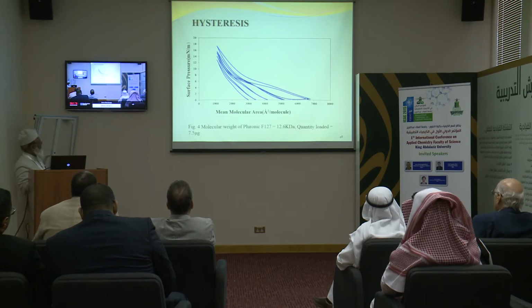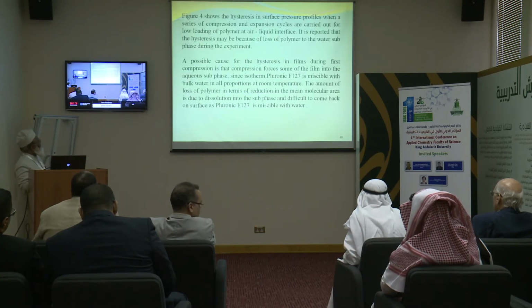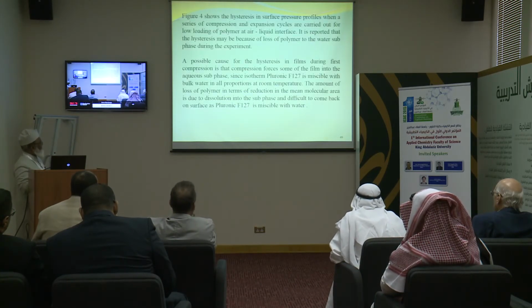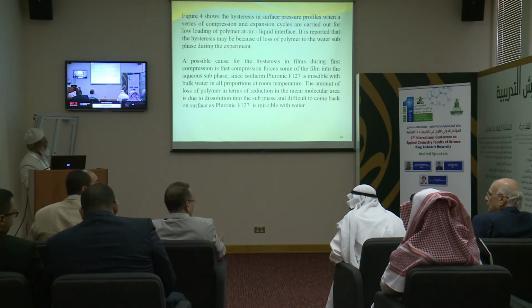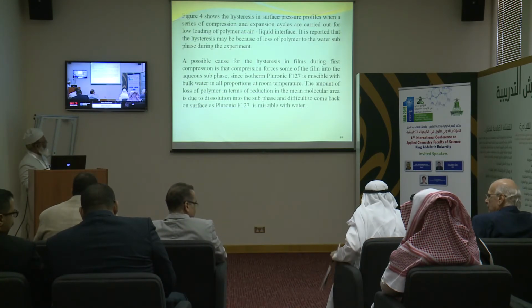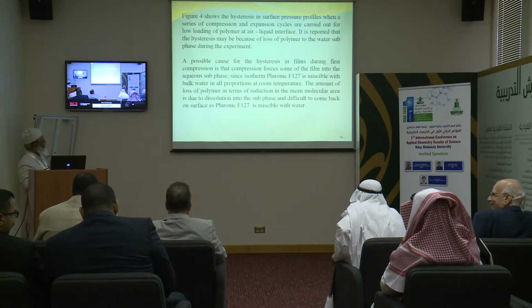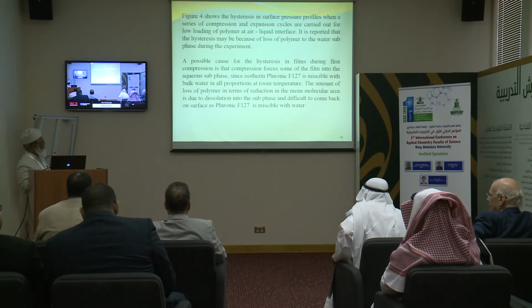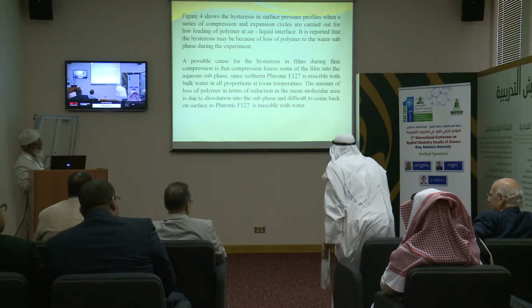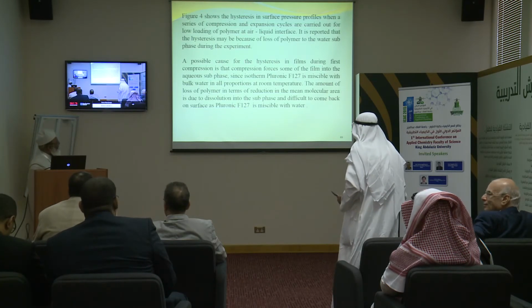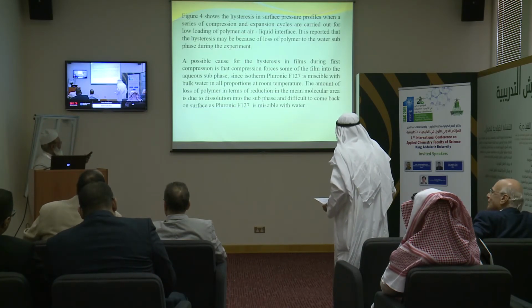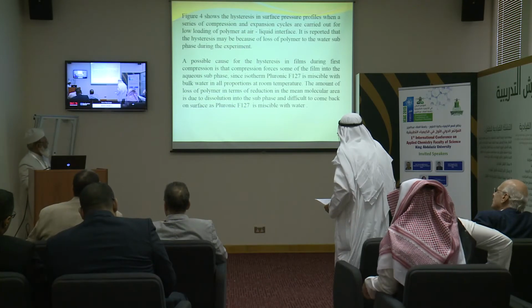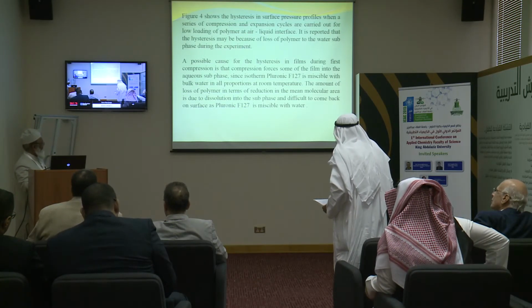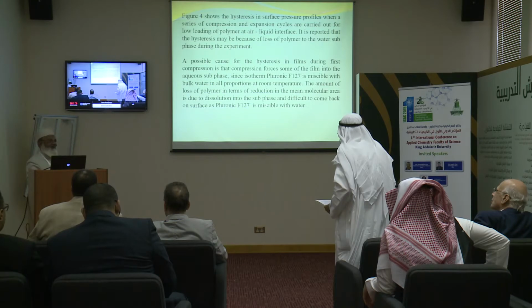This is regarding hysteresis, and you see that a possible cause for the hysteresis in the film during the first compression is that compression forces some of the film into the aqueous subphase, because Pluronic is miscible with bulk water in all proportions at room temperature. The loss of polymer, in terms of reduction in the mean molecular area, is due to dissolution into the subphase and difficulty coming back to the surface, as Pluronic is miscible with water.